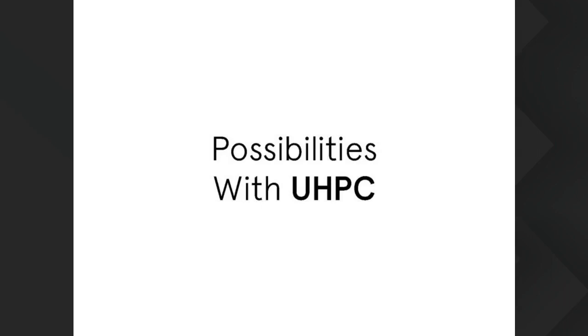How long does UHPC take to set compared to conventional concrete? We generally demold the concrete products we've cast in 24 hours, and in about 1 or 2 days, it actually gets about 30 to 40% of the strength, or maybe even up to 50% of the strength, and then eventually it catches up on strength. So the products we cast are generally handleable after 24 hours.